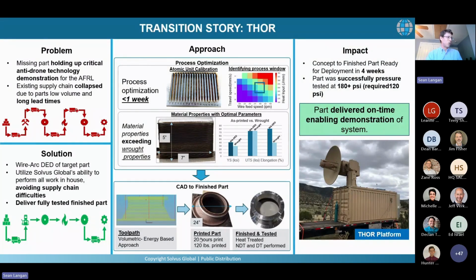This part was printed in 20 hours. It was 120 pounds printed. We were able to finish and test the part. It performed successfully one full step above the pressure requirements it had. So we went from concept to finished part to deployment in 4 weeks, and the part was successfully pressure tested to 180 psi, when the requirement was only 120 psi. This allowed for an on-time demonstration of the system. This is the kind of work we do fairly frequently at Mammoth. There are a lot of things I can't share here that I wish I could, but I'm always happy to talk to people about it.